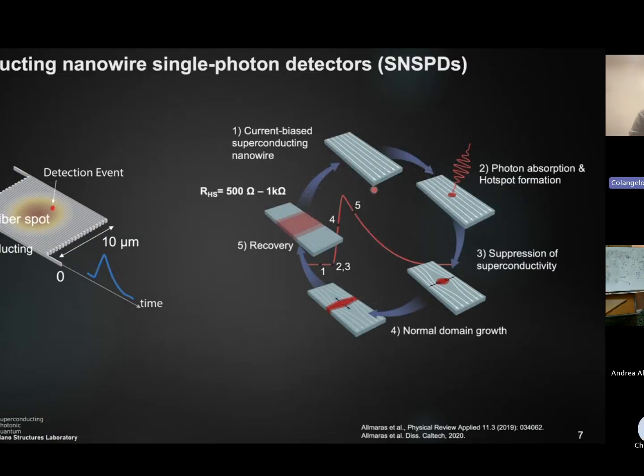Now, the working principle is really amazing. So we do have a superconducting nanowire. It is in a superconducting state. So when we flow current through the nanowire, we have no resistive drop, so we have no voltage. When a photon comes, it breaks the superconductivity and generates a resistive region that then expands across the nanowire. This resistive region is between 500 ohms to 1 kilo-ohm. And so this resistive region pushes out the current to the load, and this generates the traditional pulse that we associate to a photon being counted. And then after a relaxation, the nanowire is ready to detect again.